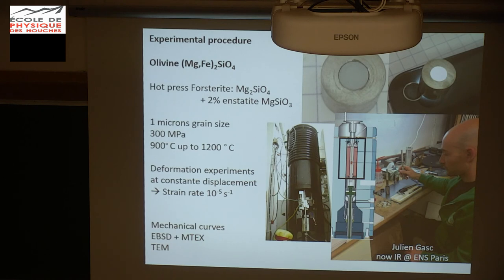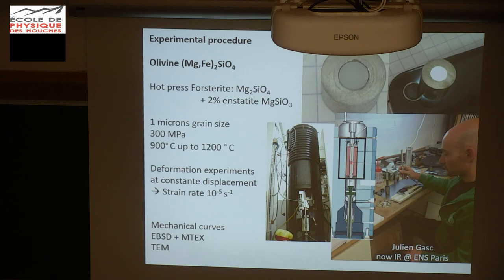This is how this very nice, almost nano grain size forsterite looks like. We have some mechanically weak metal sleeve around it, and you can put it on a light source and it's very nicely translucent, so the grain boundaries are really, really tight — a very nice starting material. This is the hot press vessel we are using. There's the outside part, the inside part, and we'll place our little samples right in the center.